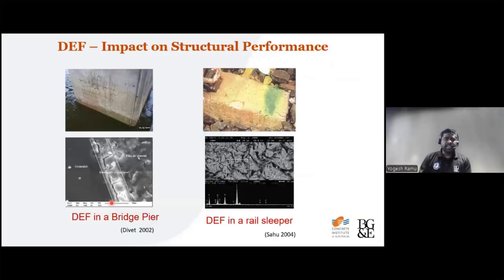So, like I said, it could impact the durability of structures. I like to explain it through a couple of examples. Here, this is a bridge pier located in France. You can see the bridge pier is exposed to water, and you can see a lot of map cracking in the surface of the concrete. When people took out some samples and tested, what they noticed is a lot of ettringite precipitated between the aggregate and cement interface. So this could lead to durability related issues and potentially reduce the service life of concrete.